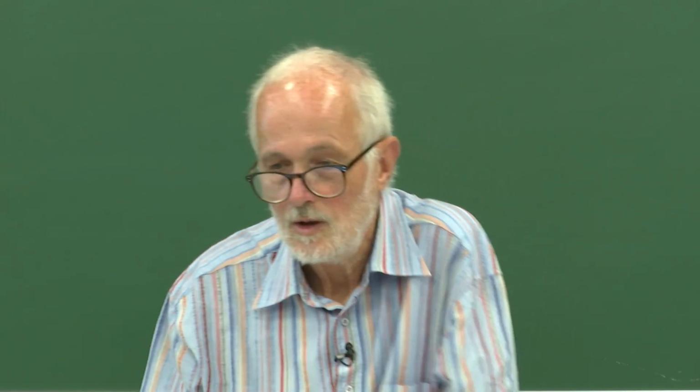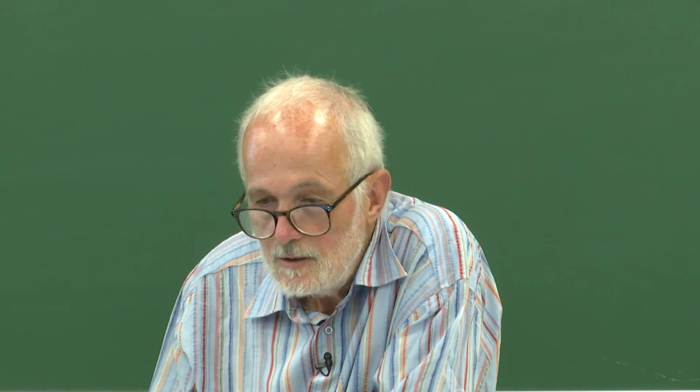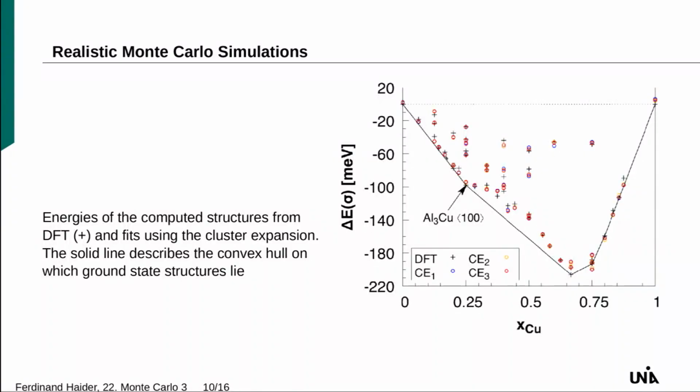Yeah? And in particular for the red ones, you see that they nicely fit these ab initio energies. So that's one step. Here's one lying out. It's strange. But most of these values correspond nicely. And also here in the interior, you find good correspondence. Okay? Now what is this straight line or this set of straight lines? That's a convex hull.